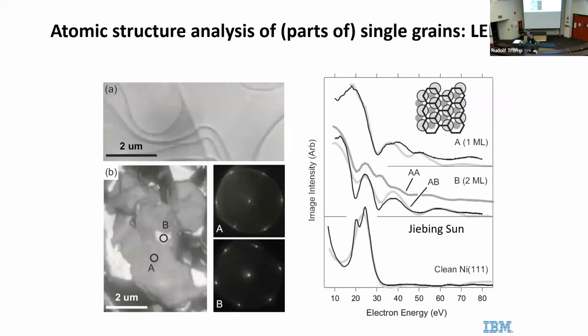So here's the same sample. This is the clean sample, and we're now going to measure the reflectivity of the 0th order diffracted beam. So the electrons hit the sample, they diffract, and there's a specular beam that comes back, right? So no parallel momentum transfer. And we're going to measure the intensity of that electron beam as a function of energy, the landing energy of the electrons. So we see that at about 20 eV, there's a big peak in the spectrum. We can also measure that in area A, where we have one monolayer of graphene.